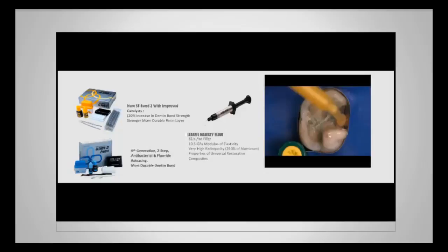The first thing we're going to do is come in and scrub our etch prime on all the dentin. Now the enamel is not critical here because we're going to bond to that enamel later. So we really are focusing on the dentin. It's going to get on the enamel, and that's okay. We scrub that in for 20 seconds, and then we air it thin, thinning it out a little bit. After the gentle airing of the etch prime, we're going to come in with the bond itself. And we're going to scrub this bond into the dentin for 20 seconds as well. We're going to really work this into the dentin. So we'll watch as that happens.